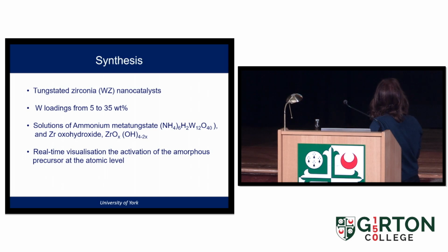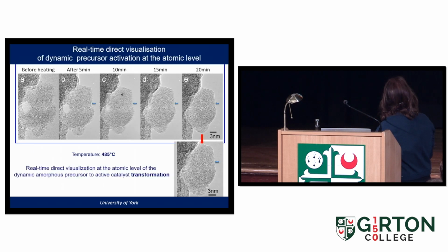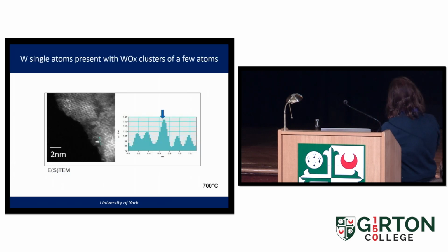This is tungsten on zirconia, and we use different loadings. We basically make it with ammonium metatungstate and zirconium oxohydroxide, and we look at it in our ETEM under real-time conditions. You see, after about half an hour, this amorphous clump becomes really crystalline, and at 700 degrees C, it becomes much more crystalline. You get zirconia grains and these atoms of tungsten and atom clusters as well.